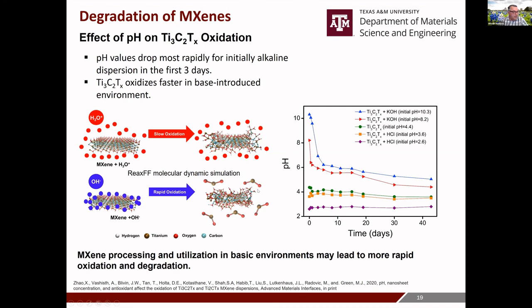And then the molecular dynamics modeling shows that in the case of the OH groups, when we put MXenes with them, they tend to completely attack the MXene nanosheets, while H3O+ groups mostly arrange themselves around the corners. So what we believe is happening, when we have long OH groups that are highly attached to the MXene nanosheets, is that they cause deprotonation mostly of OH terminal groups, giving you a water molecule and an unbonded oxygen, which is very, very reactive and starts the oxidation process.